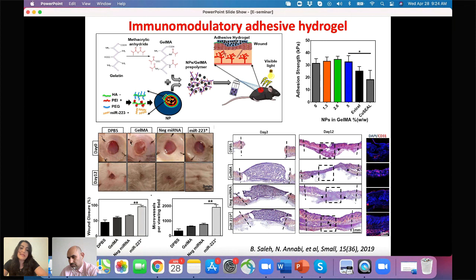Then we test different formulations of the hydrogel in our wound closure model in mice. So here we tested different groups. These are the wounds that we created on the back of the mice, and then we apply PBS as our control. This is a PBS treatment, and then we apply our hydrogel without microRNA and our hydrogel containing the optimized concentration of miRNA. And then once we look at the wound closure, we observe that the wound closure percentage was higher for the group treated with miRNA as compared with just the bioadhesive and the PBS group.